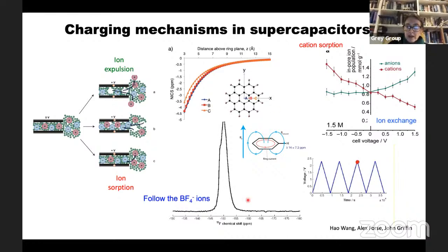And so what you're watching here is a supercap, and you're watching the fluorine NMR. So I'm looking at a BF4 minus anion, the fluorine signal of this anion that's in an electrolyte comprising an ammonium ion and acetonitrile. And I'm watching the fluorine as I'm charging this thing positively and then negatively. And this is the signal of the ion that's actually in the pore. And what you're first of all seeing is a shift to the right, and then it shifts to the left as you're charging up positively.